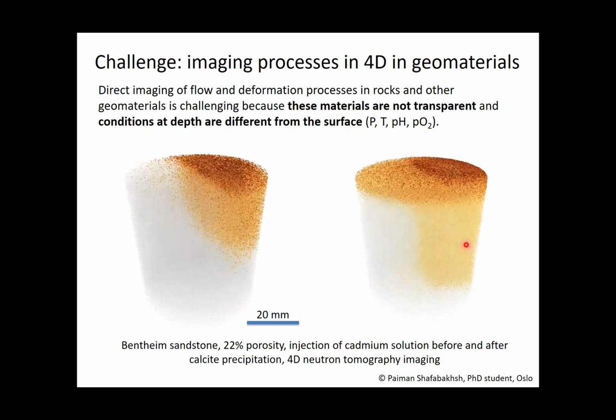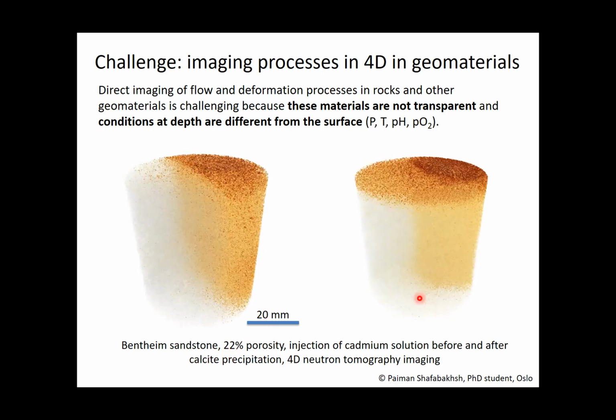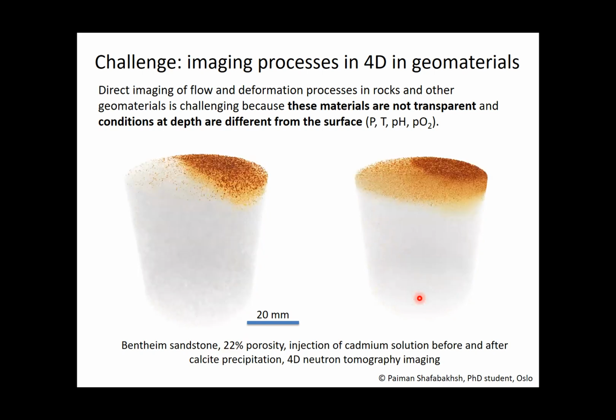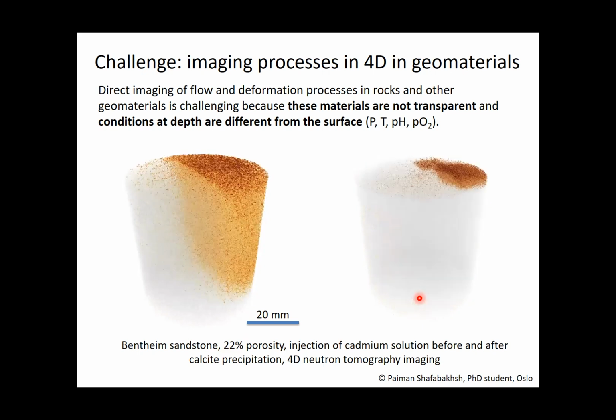And on the right side is the same sample in which we have injected a solution that precipitates calcite, so it clogs part of the porosity. The porosity will go from 22 to 20%. It will change how the two fluids will mix at the interface between the two systems. So this kind of thing can be imaged here with neutrons, and as you see, we see the fluid and we almost don't see the rock.